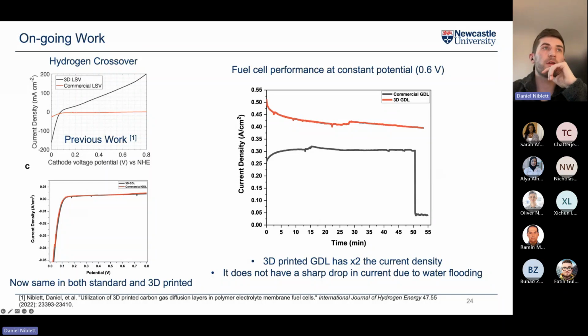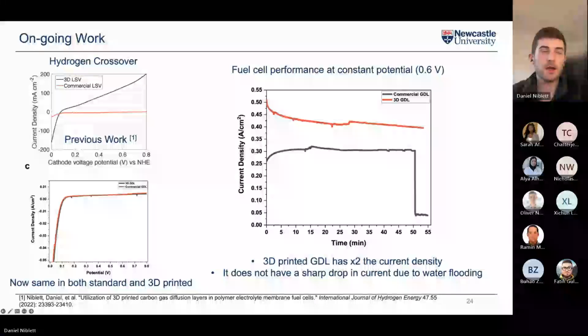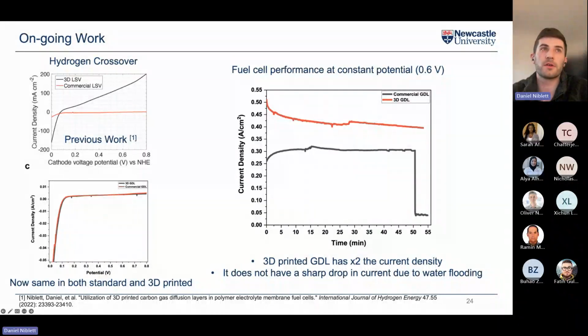And compared to previous work where I've used a 3D printed material, I had high hydrogen crossover due to membrane damage. In this work, we've now been able to get the crossover of hydrogen, which is indicated by these lines on these figures on the left, the same as the commercial GDL material now, so we've improved that.